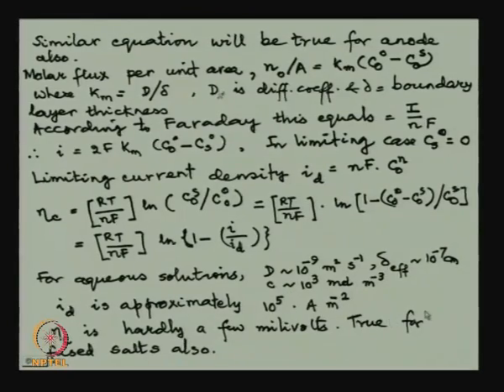Now, what are the implications? Implications are that if metal deposition is diffusion controlled, which is the fact in most metal deposition processes, in that case we change the electrode potential at the surface, but change it very little, by a few millivolts. So, the voltage requirement does not change, but that phenomenon gives rise to a limiting current condition, and we can calculate the limiting current in most cases to be about 10 to the power 5 A per meter square. So, you see that a simple phenomenon of electrolysis, if we try to analyze it, think a little deeply, we come out with these very interesting and vital findings, and we can do quantification also, as I have tried to do.